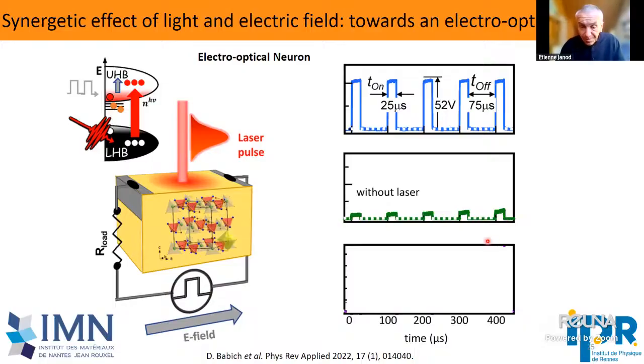And essentially no transition occurs between these 5 pulses. But if on top of this we send a single laser pulse at the beginning of the first pulse, as you can see here, you see that on the 5th pulse we have this insulator to metal transition that occurs, which is indeed an indication of multiplication of carriers promoted by the laser. Both stimuli, light and electric field, work in a synergetic way.